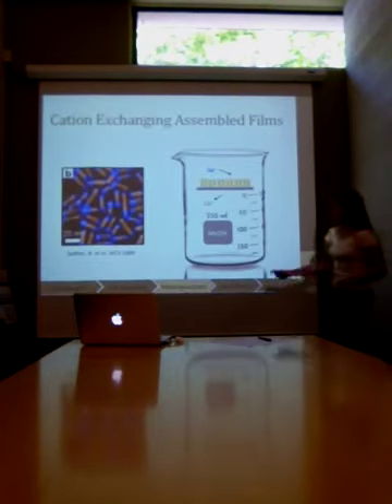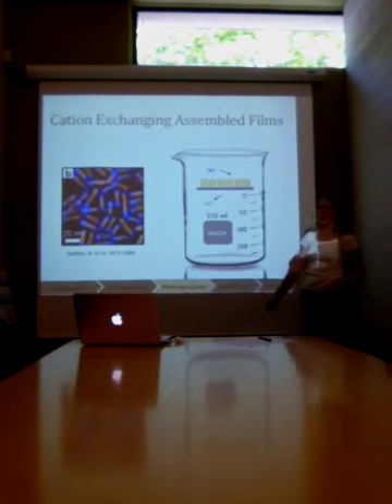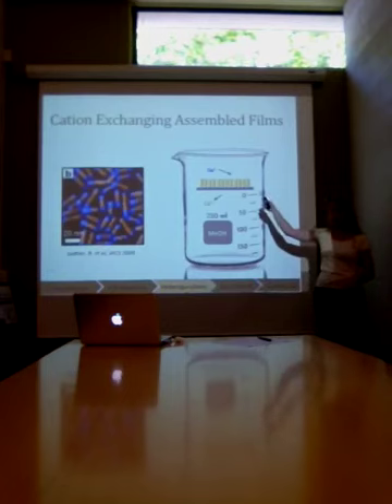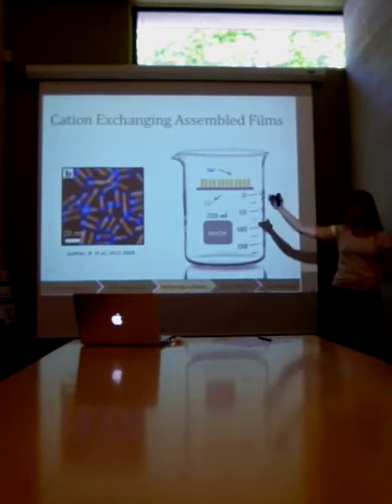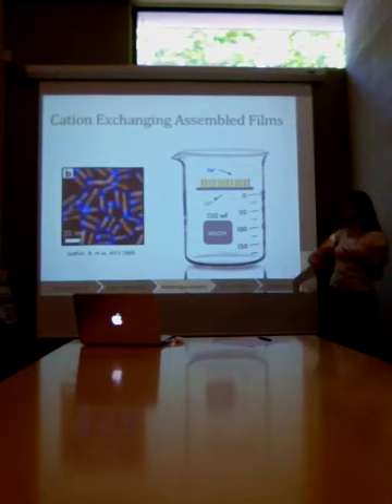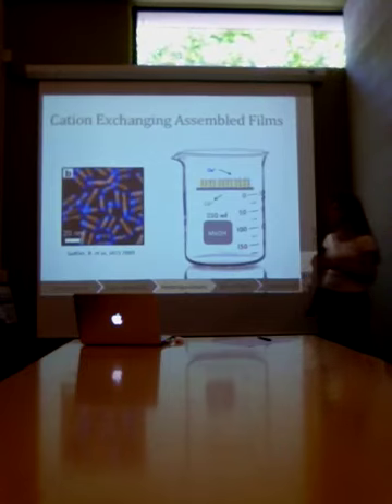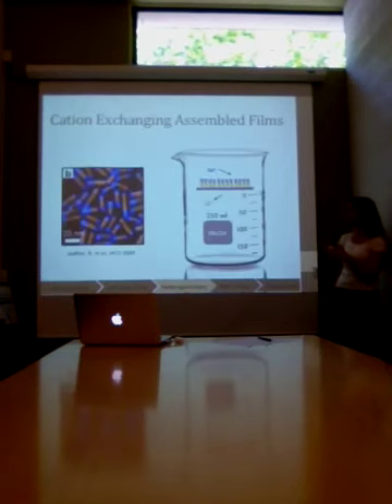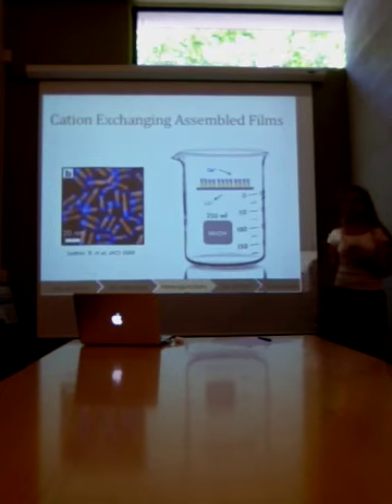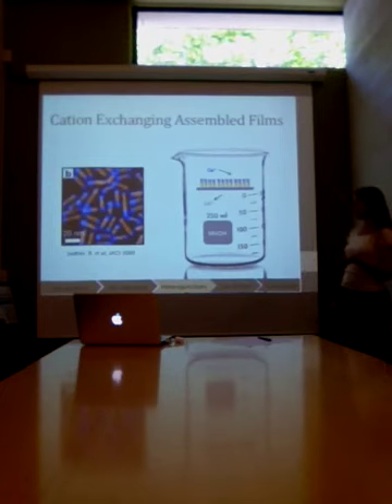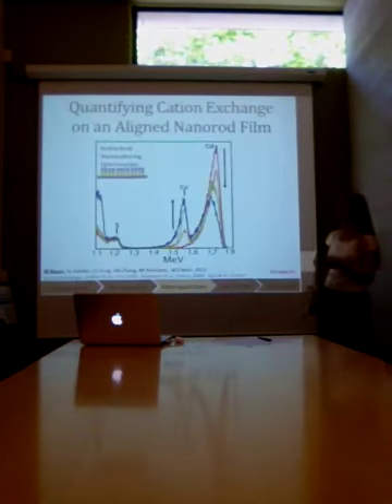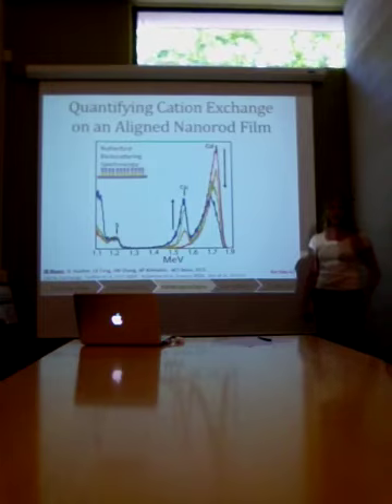So we hypothesized that if we use this method developed by Sattler et al. on our substrates of aligned nanorods, and we just dipped that substrate into a solution of copper ions, that they would exchange selectively from the top, or exposed end of the nanorod. It was pretty straightforward to carry out this experiment, but analyzing whether or not we had gotten what we hoped for was a little bit trickier. For that, we used Rutherford backscattering spectroscopy.